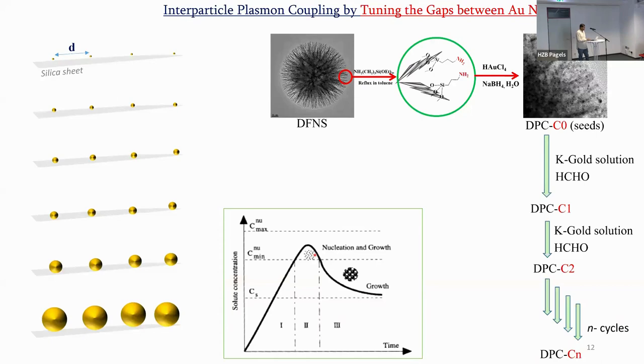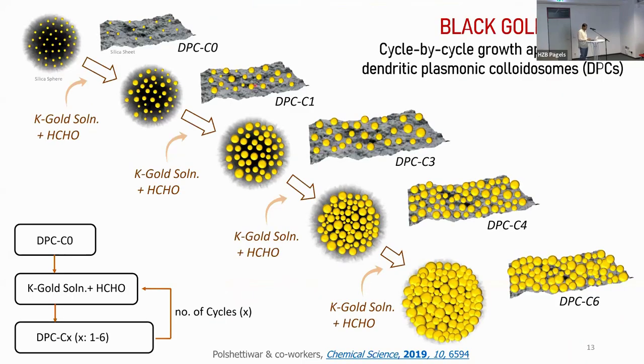So using this hypothesis, we then tried to develop this material, where we did different cycles: C1, C3, C4, C6. Now you can see the gold particles are coming closer and closer, right? And at C6, they are completely connected. In plasmonic coupling, you don't want the nanoparticles to connect. They should be apart from each other, at least 1 nanometer or 2 nanometers, so that they will be coupling. Otherwise, if they connect, it's like another particle. It's not the same nanoparticle. There will be no coupling. So we did not know what the optimal distance is to have that coupling. That's why we made a range of materials, C1, C3, and you can see they are going closer and closer.